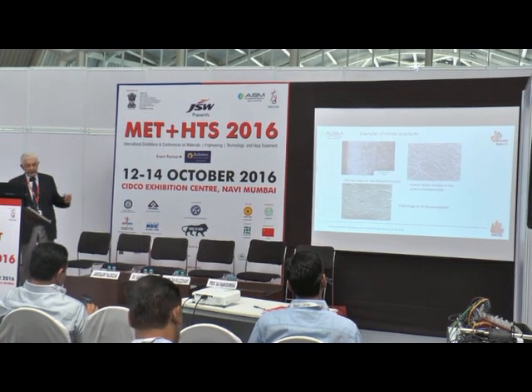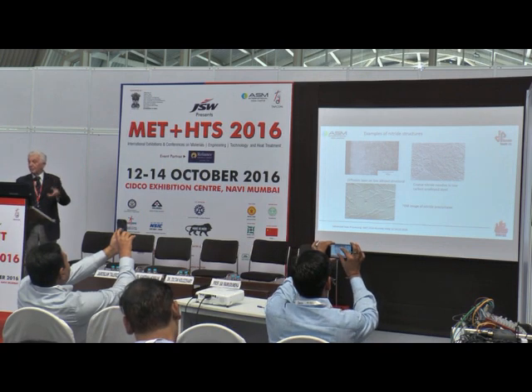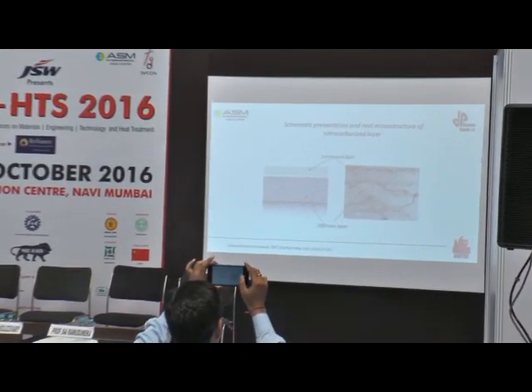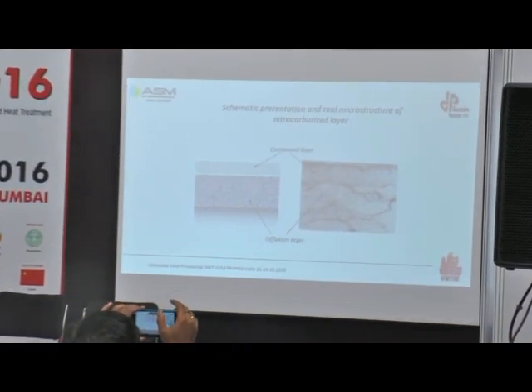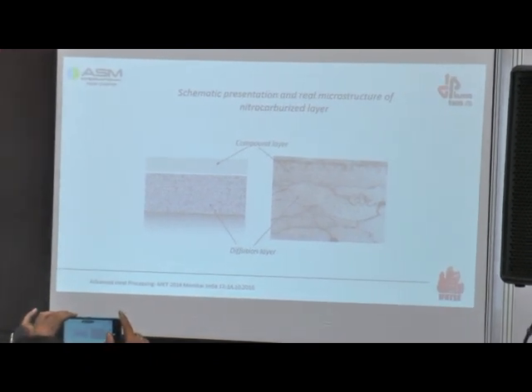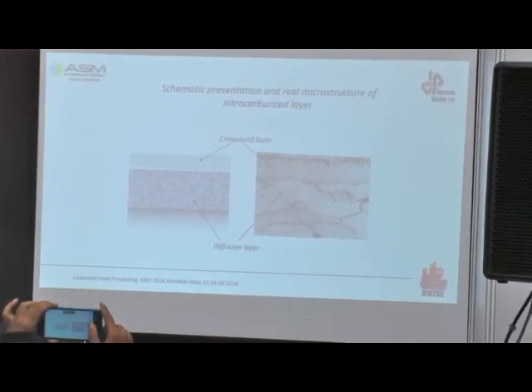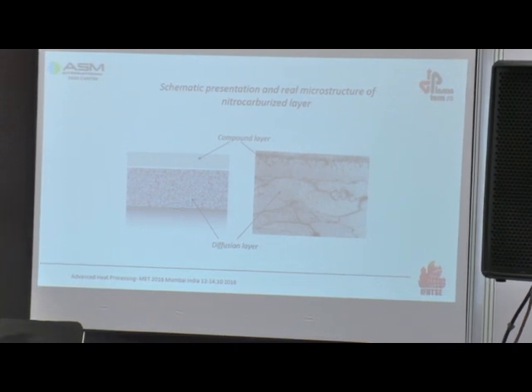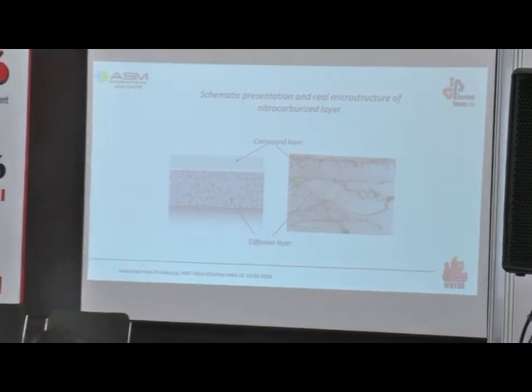Well, I just have shown a couple of pictures of the nitrided structures. Down here you have an electron microscopic picture which shows the nitride needles. This is well known, so I just put it to remind you about this. And when you talk about nitrocarburizing, I have also shown the compound layer, and I should like to emphasize one thing about the compound layer. There are many discussions about what the ideal porosity of the compound layer should be. Should it be porous or not?